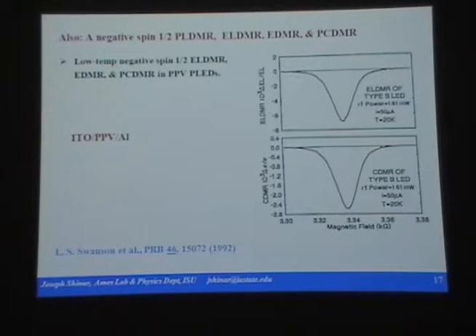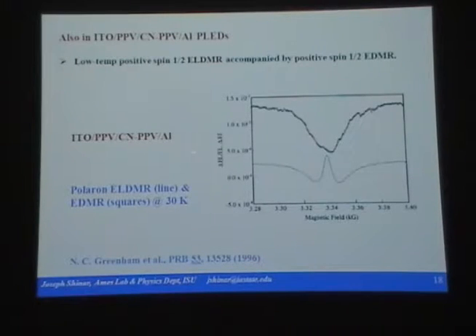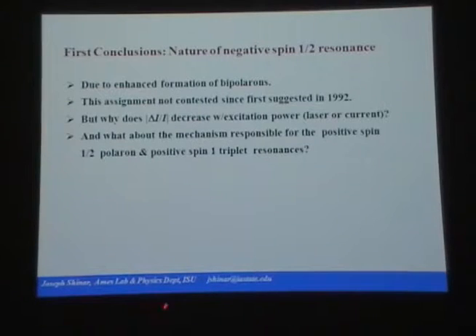We started looking at ELDMR and EDMR. Looking together with Richard Friend's group with the first generation of PPV PLEDs: all the resonances I showed up to now were positive in PL, but not in EL — EL decreases. Also the EDMR, electrically detected, is also negative. And if we looked at more involved bilayer PPV / cyano-PPV PLEDs, we saw actually both positive and negative ELDMR and EDMR. Oddly enough, this was one thing that was much easier to explain, and to my knowledge nobody has contested this interpretation over the 18 years since we first reported it.